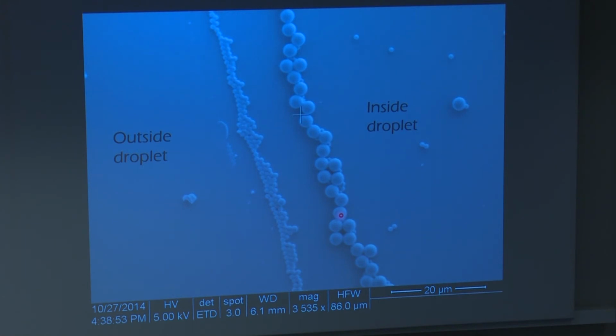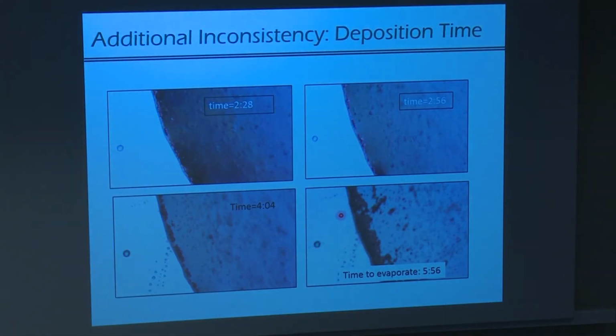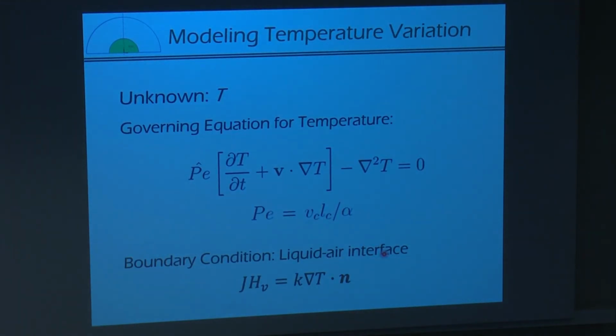So the simulations, using the computer model that we have, there are some problems. Another problem is, if you look at the deposition rate of the particles on the substrate, at time 2.28, you see very few particles near the contact line. At 4.04, there are probably a few more particles, but most of the particles deposit right towards the end of the drop drying. So the isothermal model has problems in terms of calculating the rate at which the particles reach the contact line.